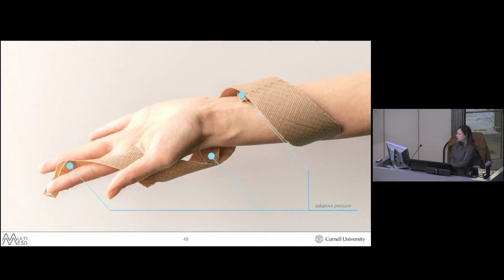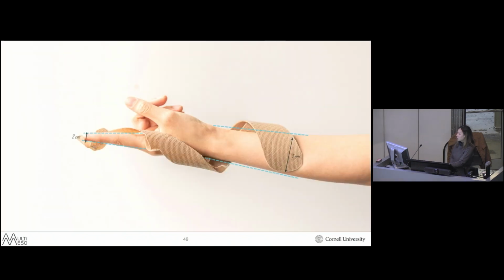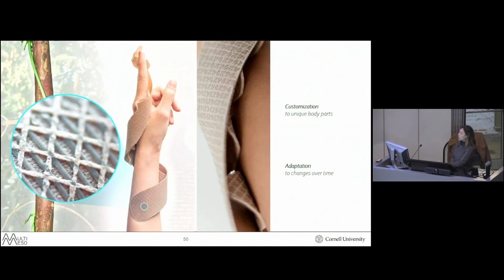So this is the design of the splint with the bioinspired mechanism, which self-tightens around the wrist and forearm at varying curvatures. And what's the most important takeaway to me is that we found that we were able to generate a similar range of forces as the air potato plant when we mimic those stipules in low quantities, which is how they are found in nature. And if we increase the number of those stipules and further delayed their actuation using 4D printing, we were actually able to measure higher forces.